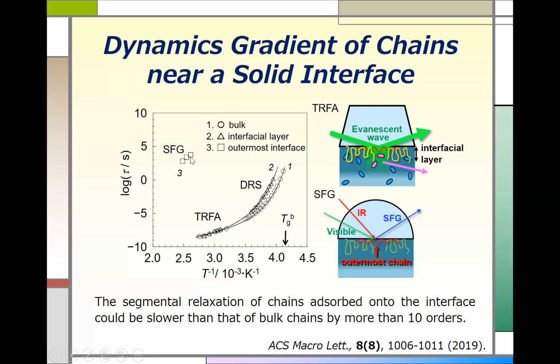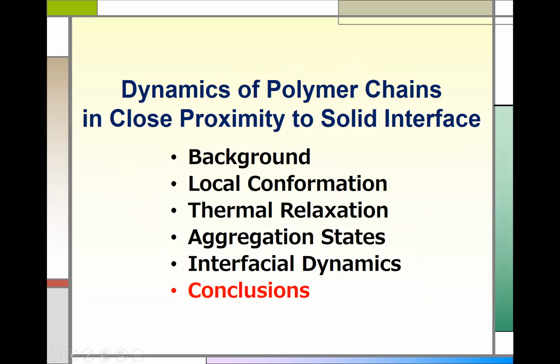This is the true interface. Let's say less than 1 nanometer interfacial region, then the relaxation time at a given temperature is going to be extremely larger. What this means is that polymer chains at the solid substrate cannot be relaxed. That's what I'm saying. So let me conclude my talk.